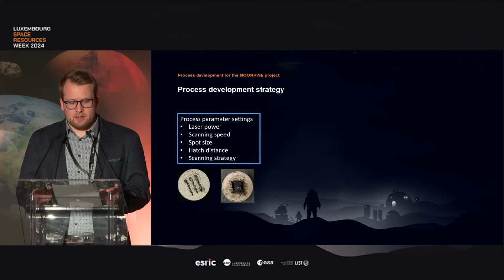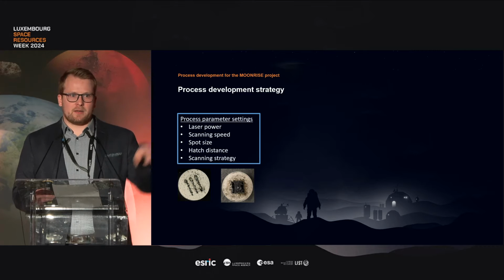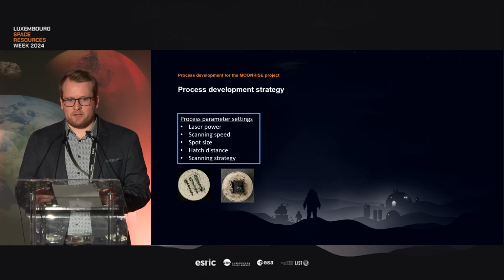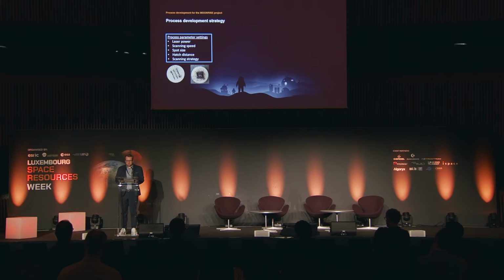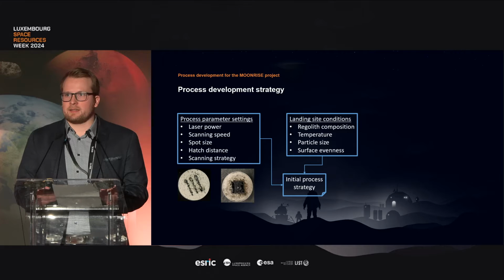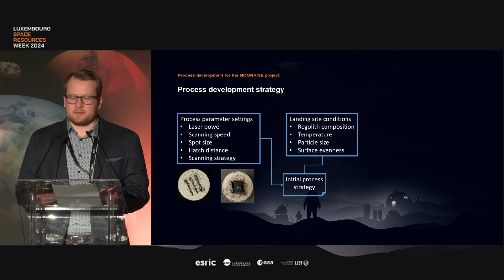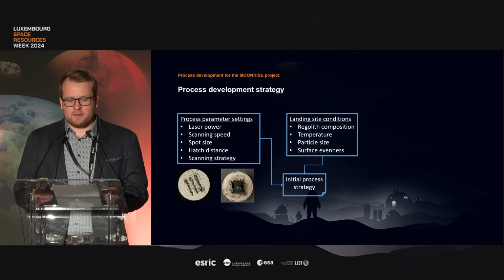The two-dimensional ones are 25 by 25 millimeters at the moment, and for these we have to develop a suitable range of hatch distance parameters, so the distance between the different vectors, and we can also work on the scanning strategy. So whether the vectors are unidirectional, or meander-like, or even other strategies like remelting, for example. When we have that range of parameters, we can research the influence of the environmental conditions on the landing site on the moon, such as the regolith composition, the temperature, the particle size, and the surface evenness.